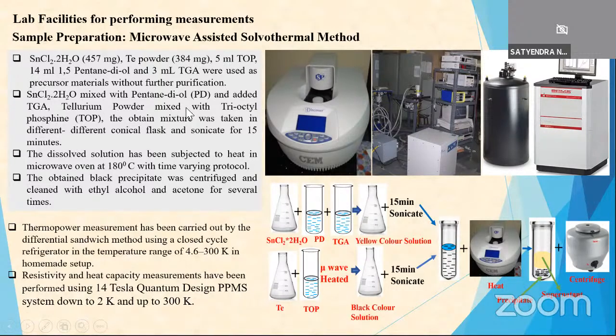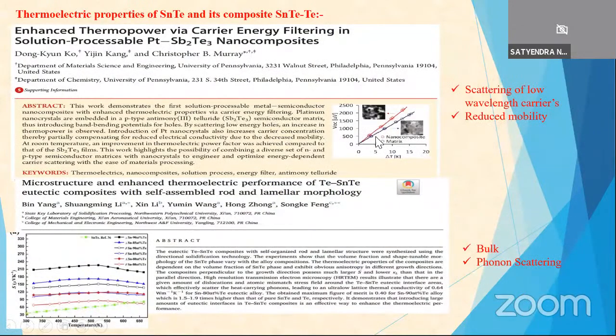Why are these composite materials interesting for thermoelectric performance? Because the high and low mobility electrons scatter from the carrier centers, due to which there is a reduction in the thermal conductivity, but there is not much change in the electrical conductivity. So due to the cumulative effect of the electrical conductivity as well as the reduced thermal conductivity, there is an enhancement in the thermopower. There are bulk reports on SnTe and Te materials which state the phonon scattering mechanism is predominantly present in the system.